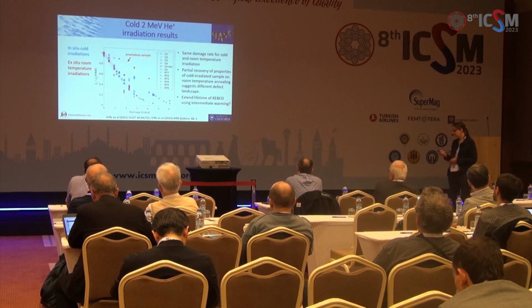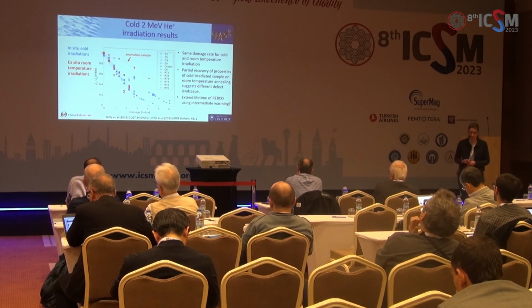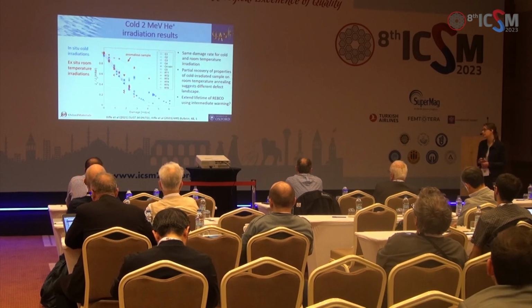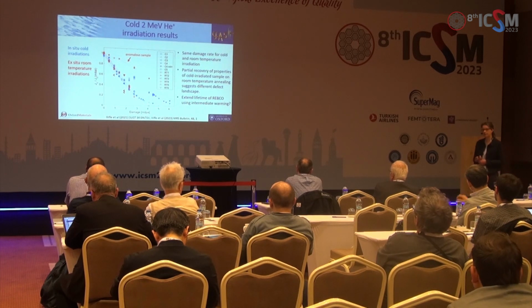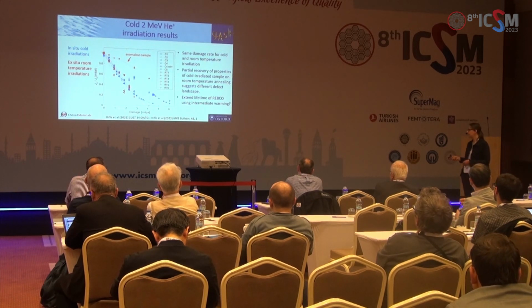So in fact, even though it looks like the damage rate is similar in these two warm and cold irradiated samples, I actually don't think the damage landscape can be the same, because we can't recover the properties of the room temperature irradiated samples, but we can get some recovery with the cold irradiated samples when we go to room temperature.